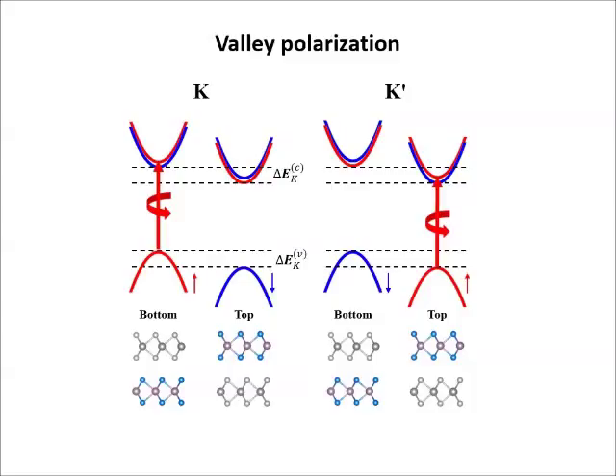And as a next step, at the K point, the spin relaxation through the interlayer scattering takes place. However, at the K' point, the spin relaxation is suppressed due to the energy barrier from the top and the bottom layer.